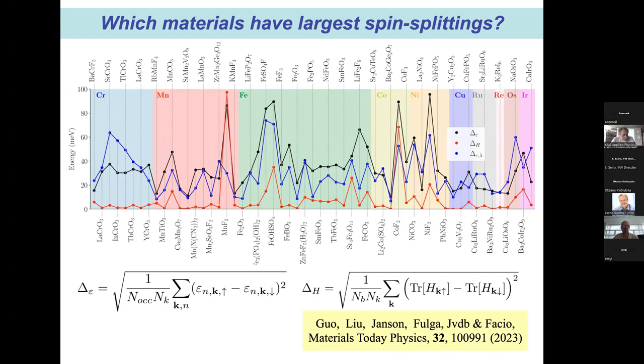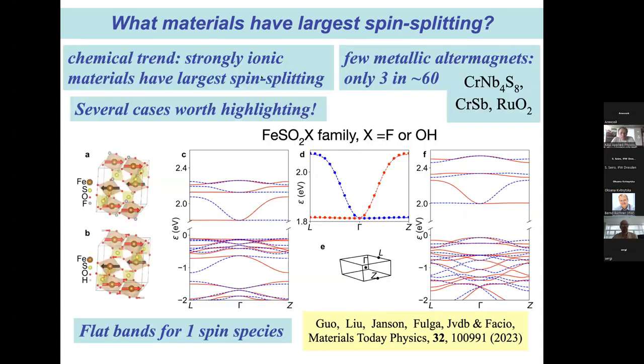So what did we learn from these calculations? That there is a chemical trend, that the strongly ionic materials have the largest spin splittings, which is probably not so amazing because they also have the largest exchange splittings. There are only few metallic ones in this database. There are only 3 out of 60 altermagnets that are metallic, which are chromium antimonide, ruthenium dioxide, and this chromium niobium sulfide.